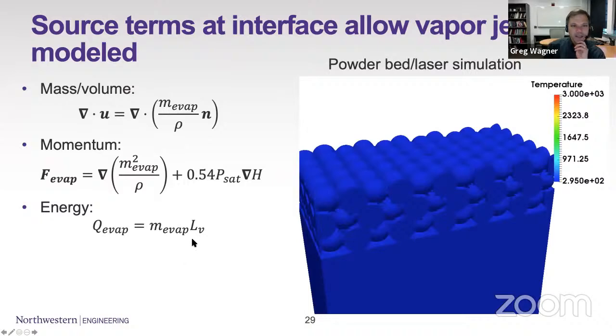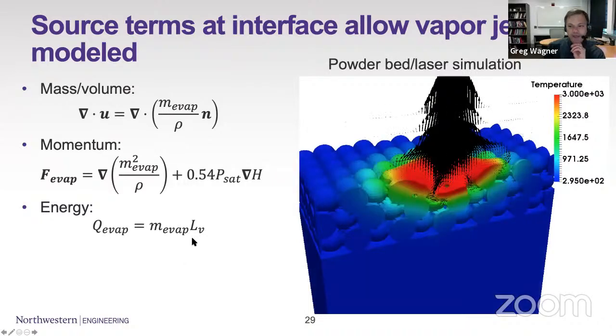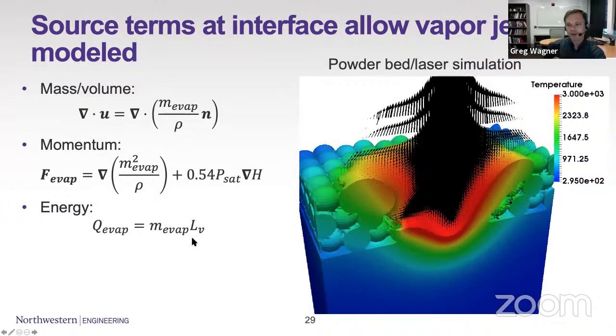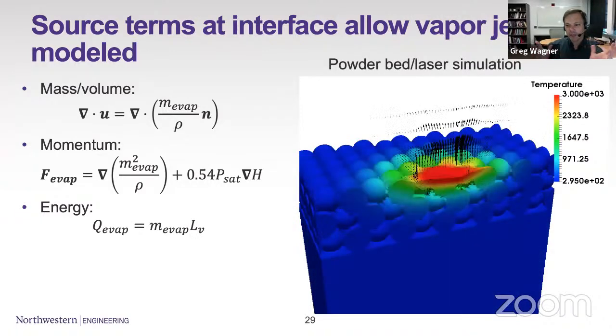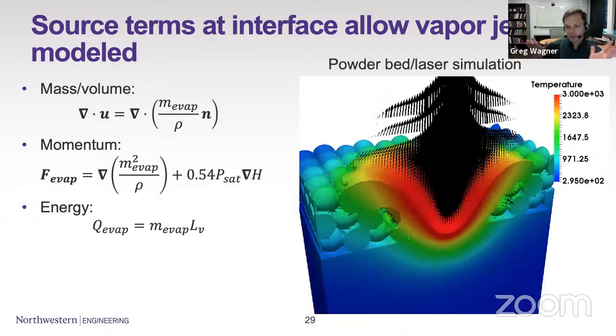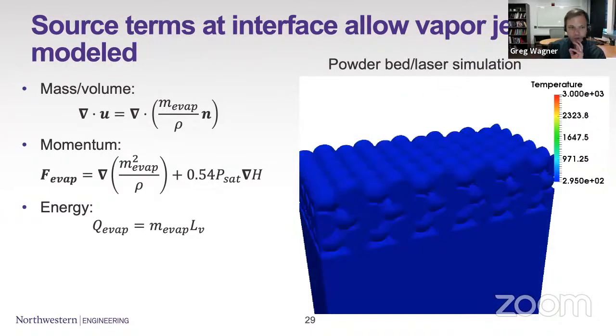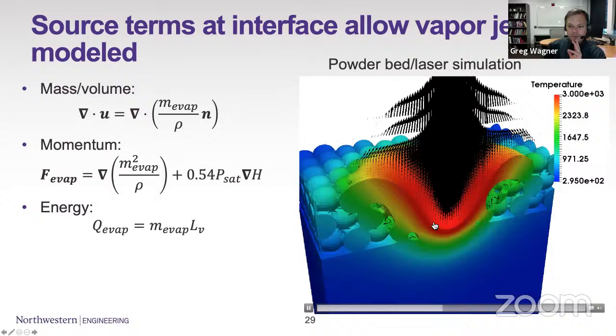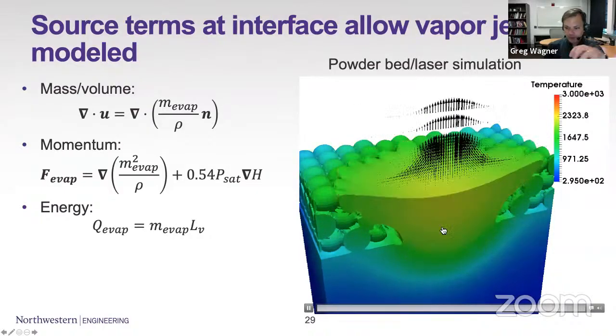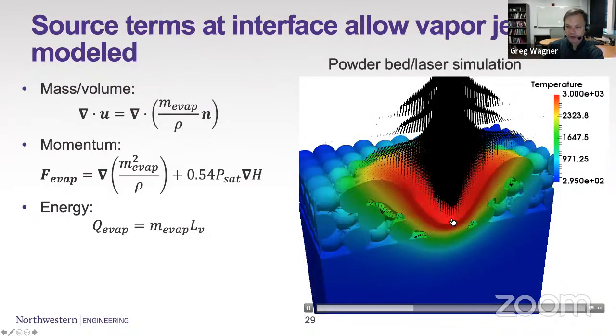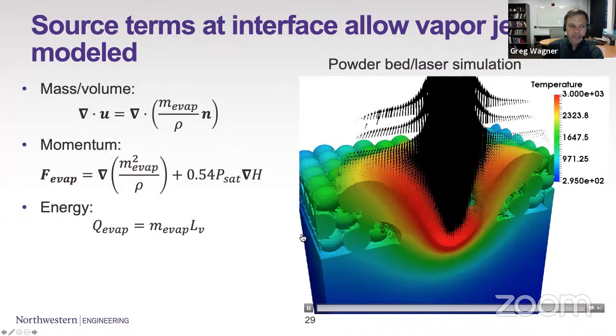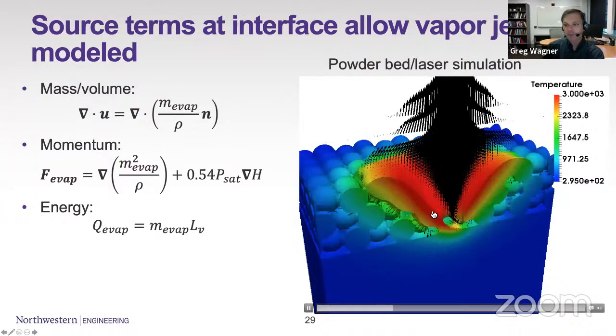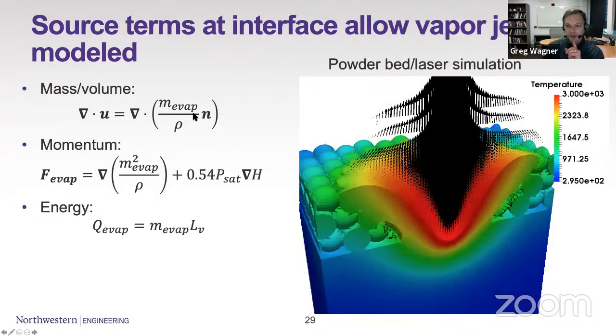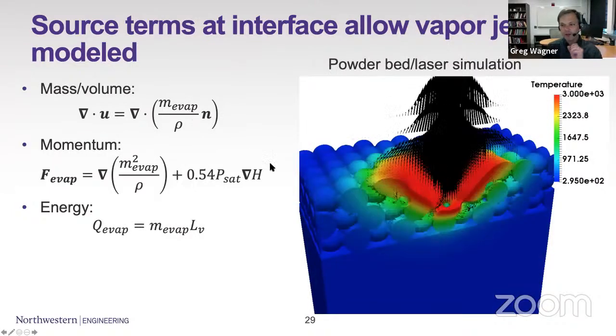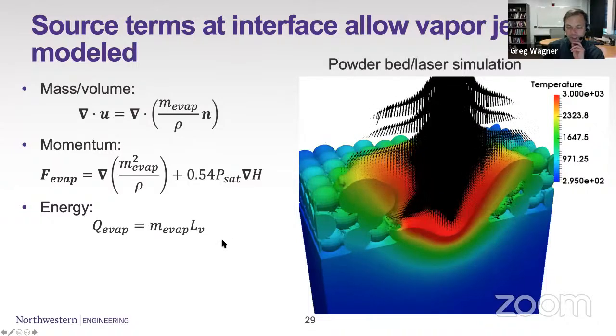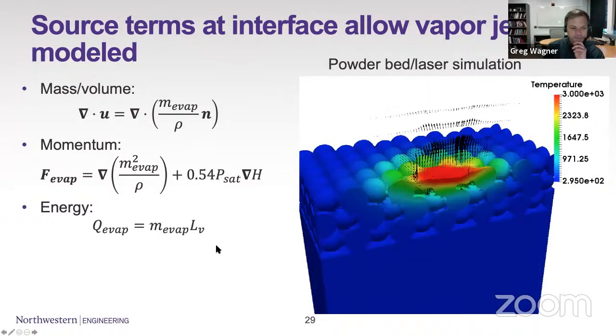All right, so finally, the interface treatment and the fact that we're coupled to this surrounding vapor allows us to capture at least a little bit of this vapor plume that you get near the evaporation region. The recoil force at the surface is giving us this keyhole-like behavior at the surface, and the coupling to the surrounding vapor through our continuity source term is giving us the vapor plume. So we can look at the combination of these and the interaction of these things.